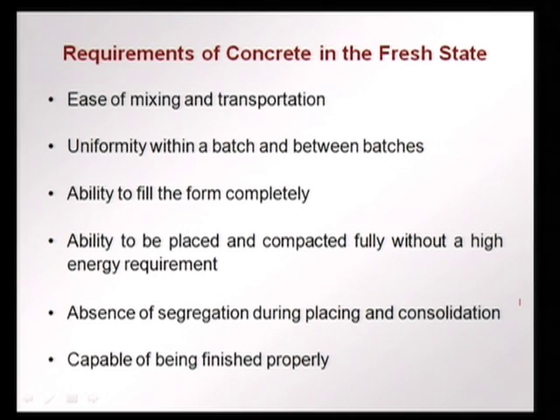The concrete should be able to fill the formwork, the molds completely without leaving any voids, and we should be able to place and compact fully without very high energy requirement, because that would mean that there would be errors and less energy used could lead to poor compaction. This is something that we would like to avoid. So, a concrete should be easy to place and compact without very high energy requirements, and ideally it would be nice to have a concrete which does not need any energy requirement for compaction. This is achieved to some extent by self compacting concrete.